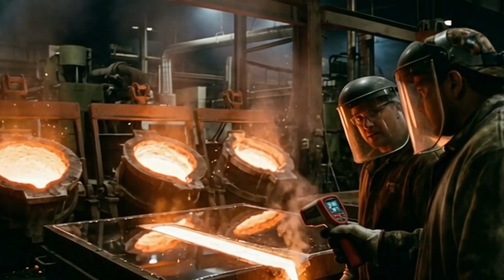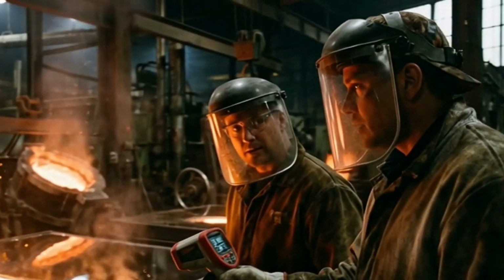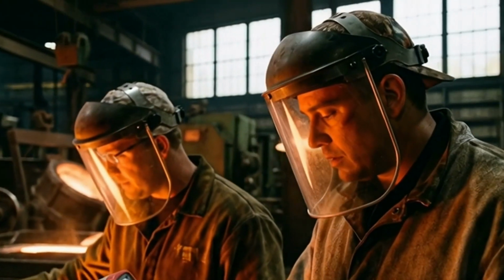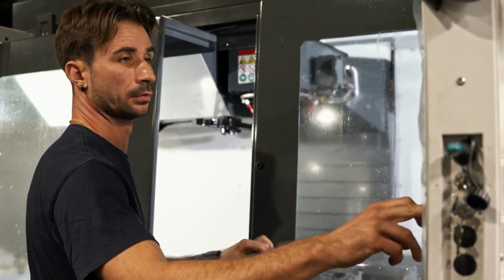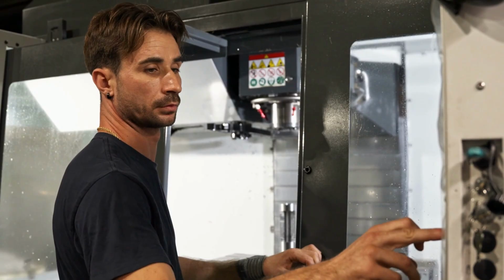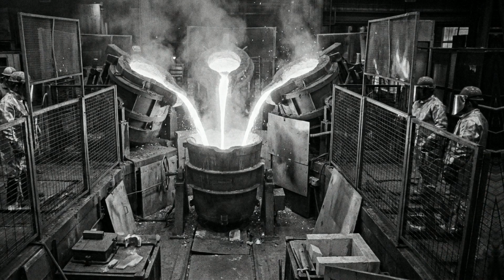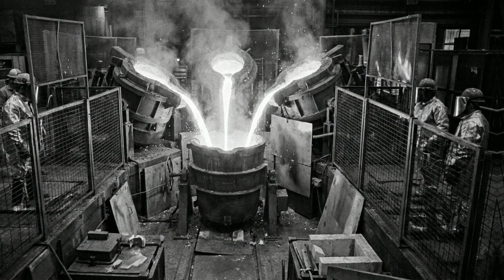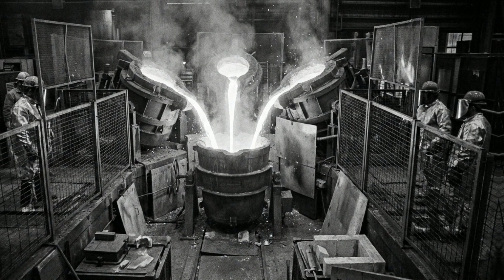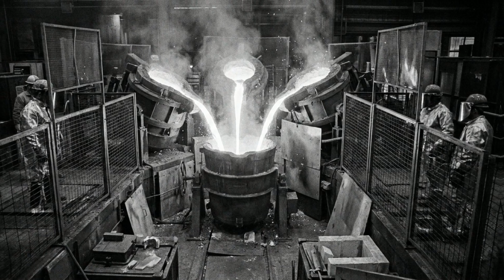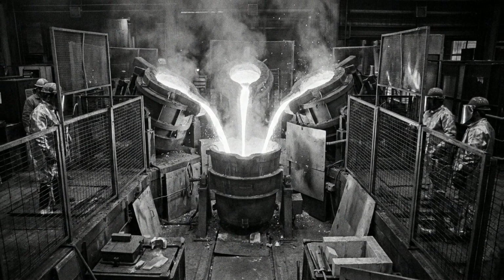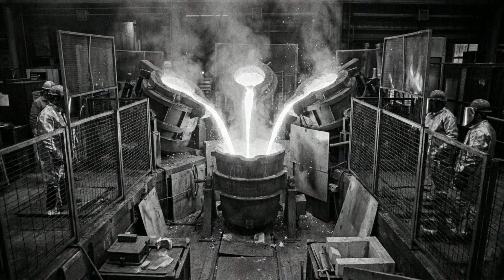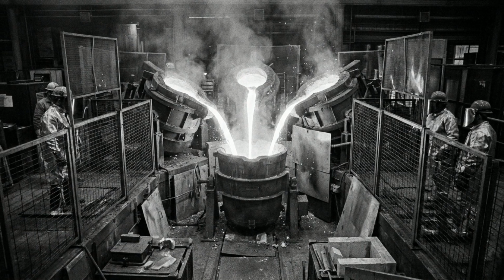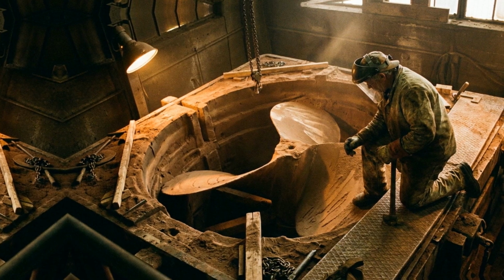The melt for a single large propeller requires furnaces capable of holding and pouring over 100 tons of liquid metal in a controlled continuous pour. Stopping mid-pour creates a cold shut, a plane of weakness where the two pours meet that will eventually become a crack under cyclic loading. So the pour happens all at once. One continuous event, moving as quickly as the mold filling rate allows, with multiple furnaces tapping simultaneously into a central ladle or directly into the mold system.